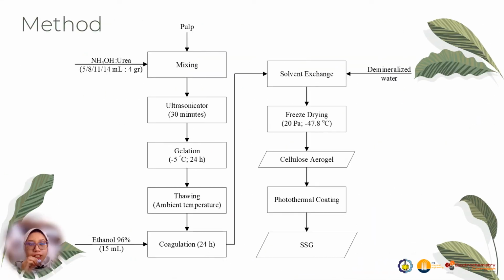The lignified pulp is then mixed with ammonia and urea as cross-linker, then sonicated for 30 minutes, then gelated at -5 °C for 24 hours. Coagulate using 96% ethanol for 24 hours. Solvent exchange using demineralized water, freeze dry at 20 Pascal. The freeze-dried cellulose aerogel is then coated using black ink to become the bilayer SSG system.